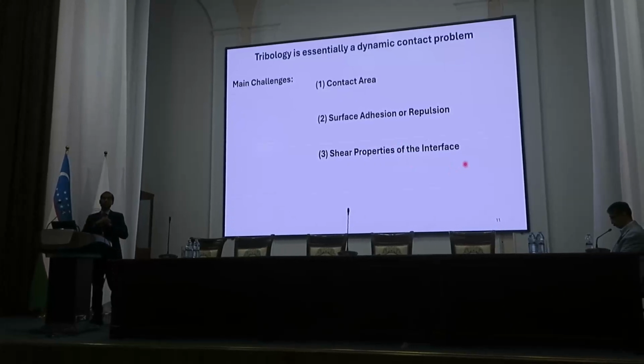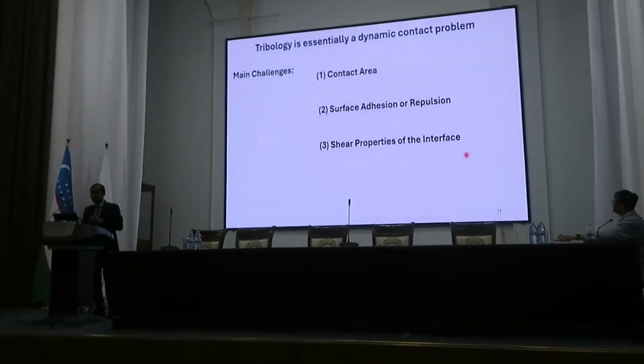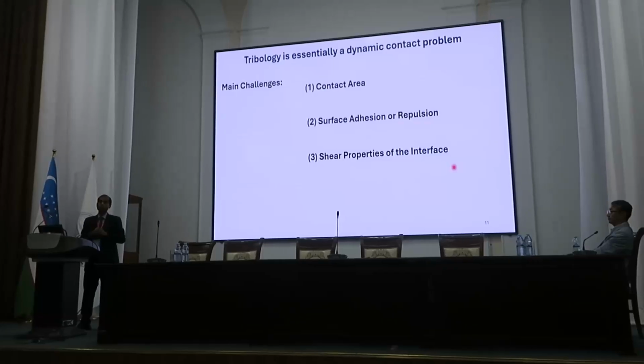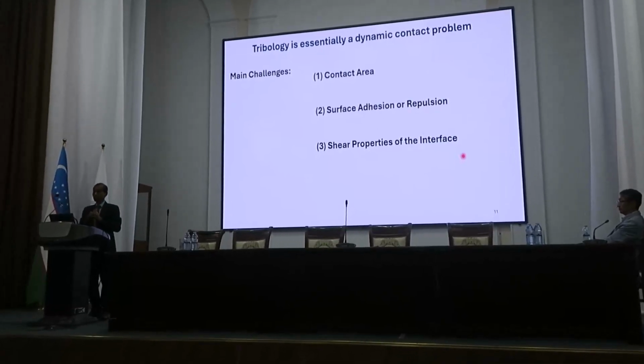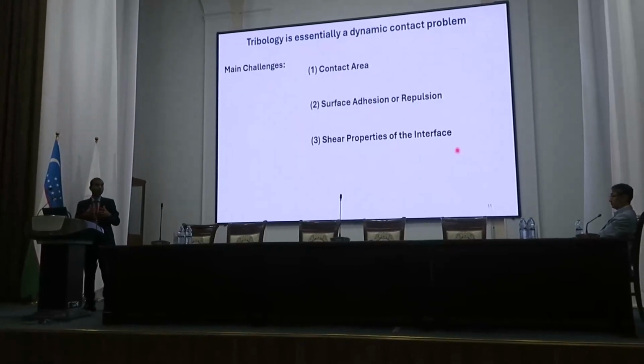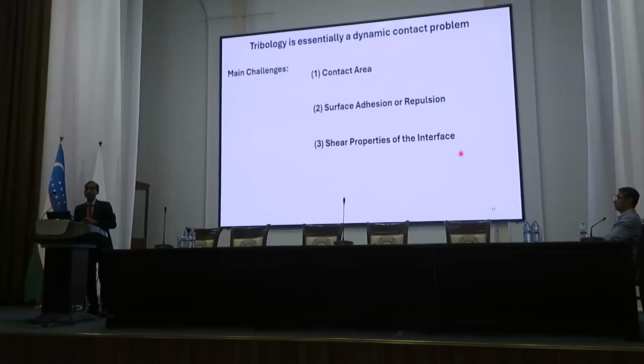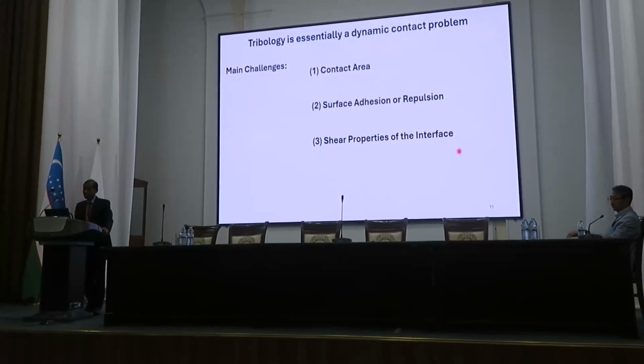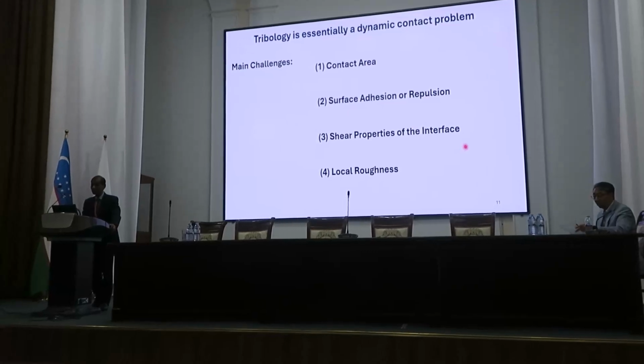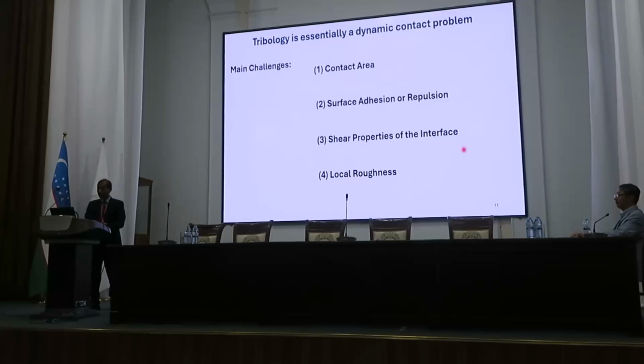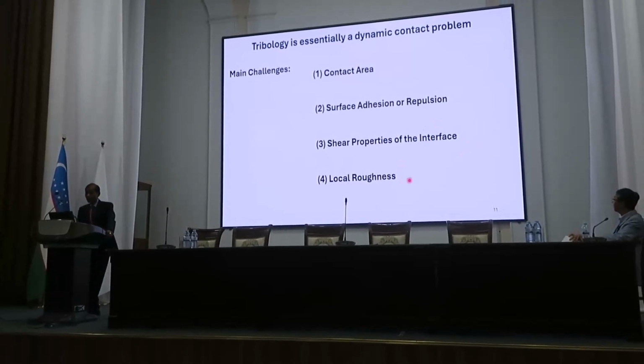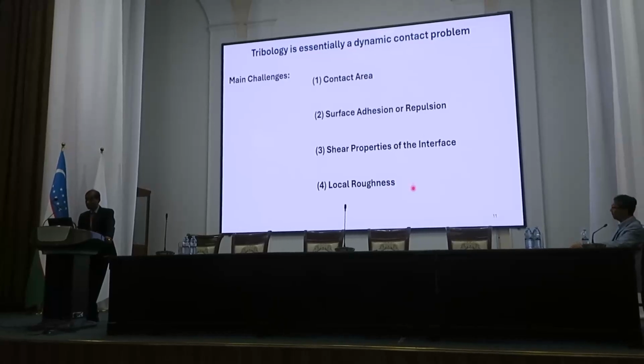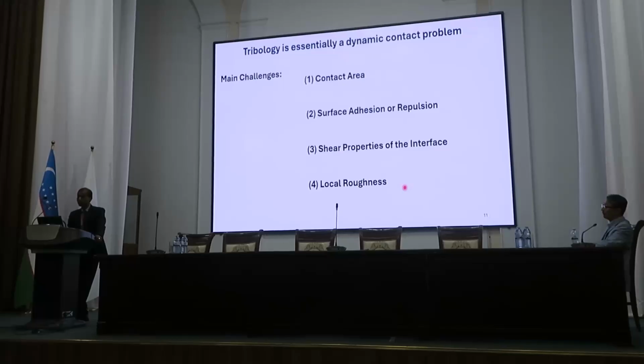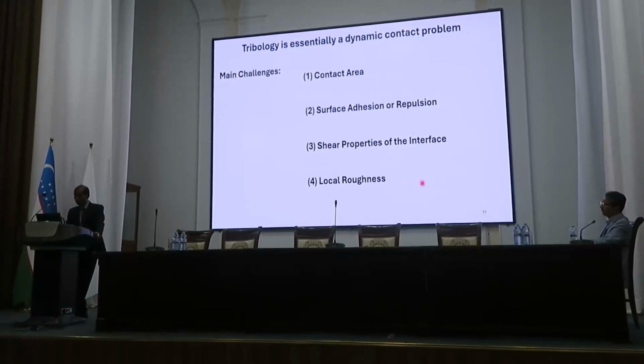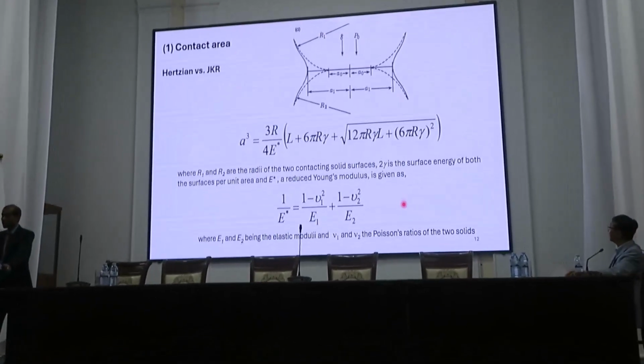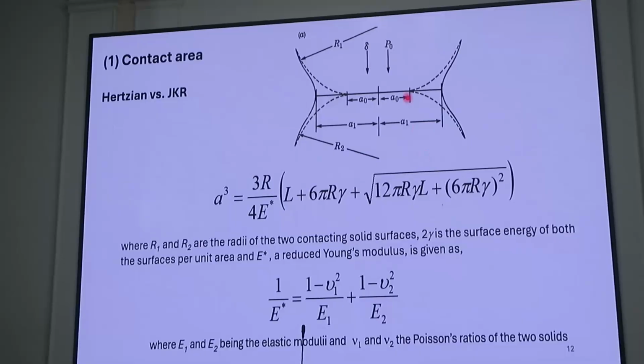Then the shear properties of the interface. At the interface, what happens? What is the shear property? That is another important issue, and shear properties will depend upon the speed, how fast we are moving or sliding, because especially the younger generation might be more active than the older generation. So you might have to think about the shear rate issue. Another is local roughness. Roughness remains a big issue, even for implants where the surface roughness is reduced as much as possible. But if we are going for a little harder material, then surface roughness will be important. These are the main four issues which are important, and I will just go through them.